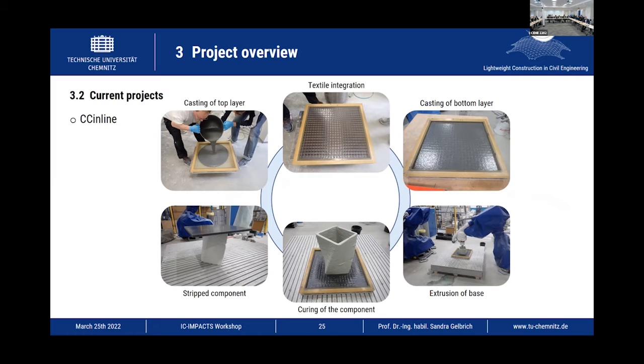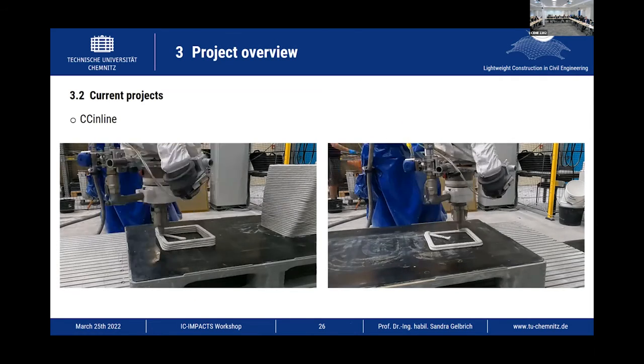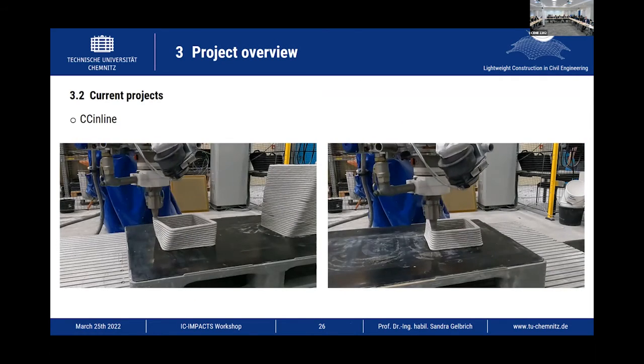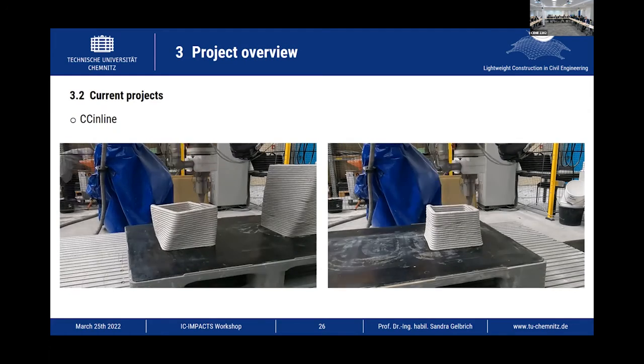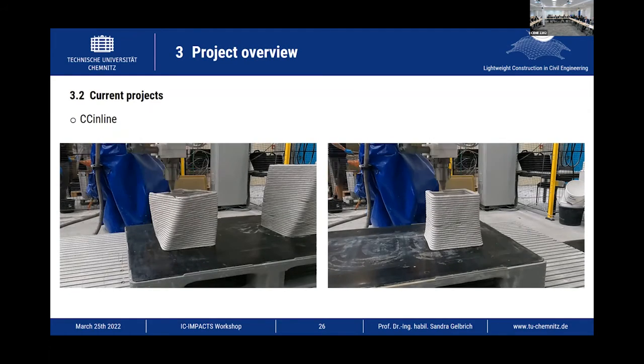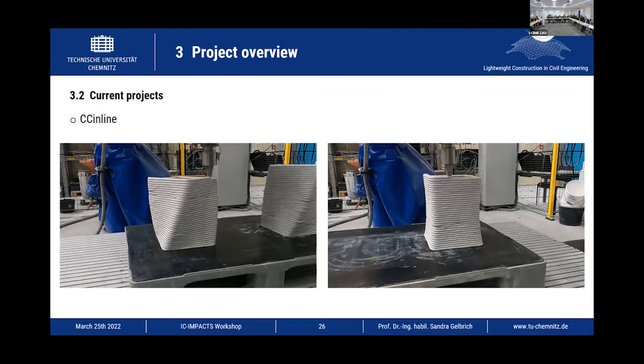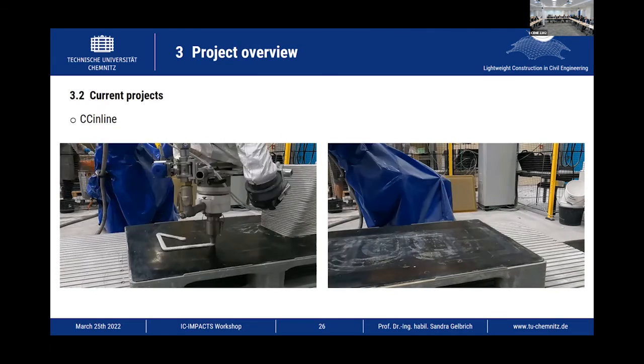The thickness of the plate is 20 mm and the height of the table 400 mm, with a layer height of 10 mm and a layer width of 20 mm. And the extrusion velocity used here was about 60 mm per second. On this slide, you can see two time-lapse videos showing the extrusion of two different variants of the table base. The production time for each of these is about 10 minutes.